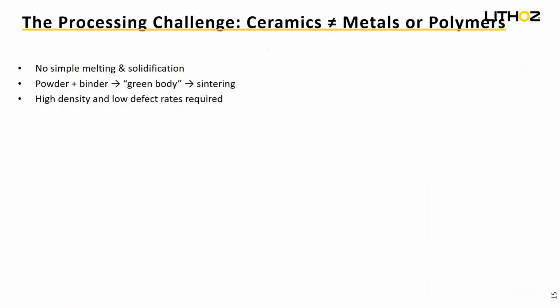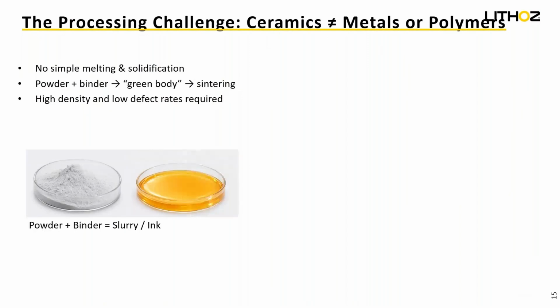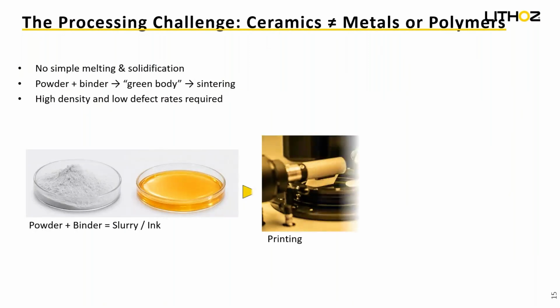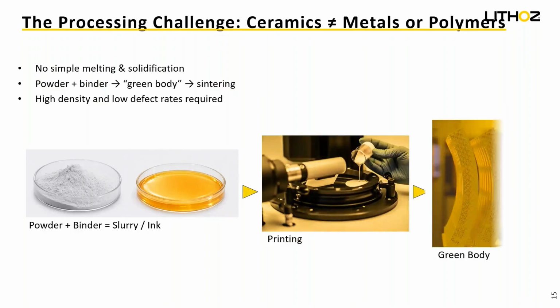Here is why the green body step is so critical. Since ceramics cannot be melted, we must work with a slurry made of powder and binder. This slurry is printed, and then we have the green body, which is still soft and full of binder. Only later, during the debinding and sintering, do we achieve the final ceramic.